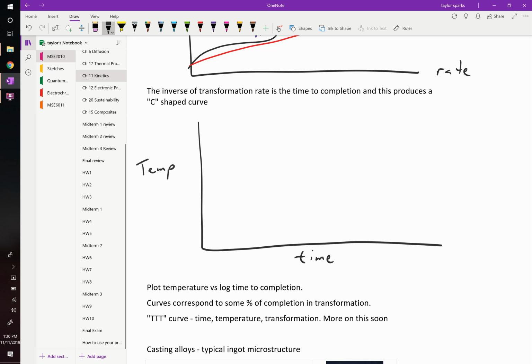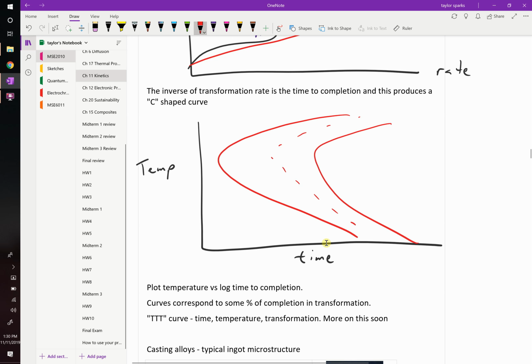And then what we're going to show on this plot is a series of different transformations, right? So you can have a curve like this, curve like that, curve like that. Now you'll notice that this looks like a C-shaped curve. It looks like the letter C. The reason why it is because transformation rate is going to be inversely proportional to the time to completion. Sometimes they write that 0.5, meaning the time it takes to be half completed, right? A faster rate, a shorter time. So what you're seeing here is lines that represent 0% transformed, 50% transformed, and 100% transformed.